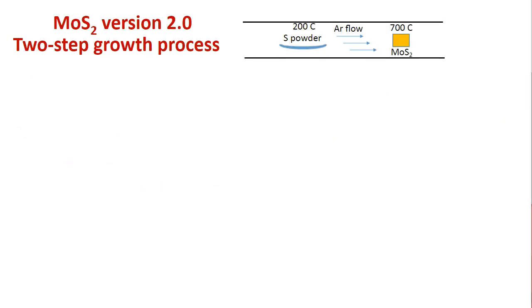So what we did next was we adopted a sulfurization step after the thin film growth. What is sulfurization? Well, we just took some sulfur powder, heated it up, and had it flow over the MoS2 thin film, which is kept at a very high temperature, 700 degrees in this case. So this process is called sulfurization. That means you essentially surround the MoS2 film in a sulfur-rich environment and hope that all the missing sulfur is replenished.